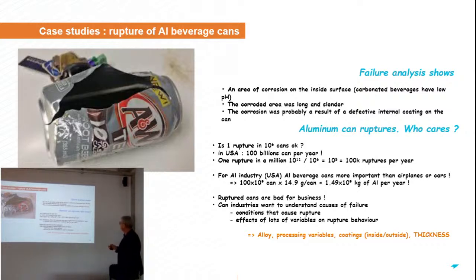You can see here the failure analysis of a beverage can. So you can see here that this can has failed, and when we analyze the problem here, we can see that we have some corrosion in the inside part of the can. The corroded area was long and slender, and the corrosion was probably a result of a defective internal coating.